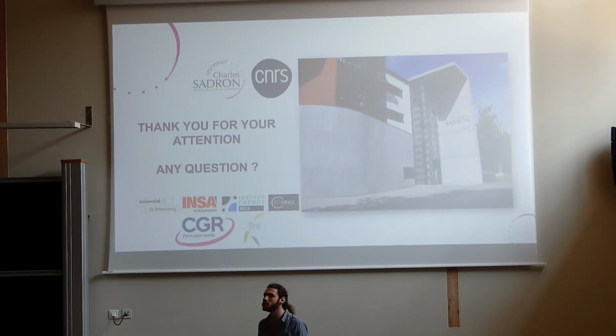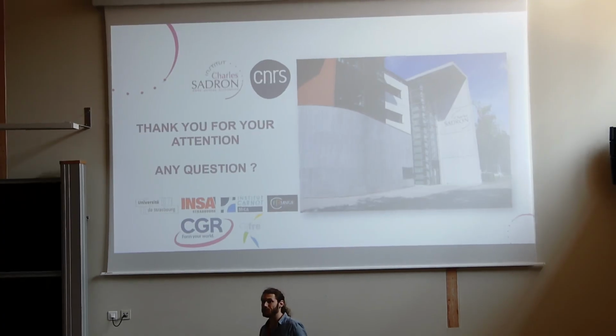Thank you for the presentation. Actually, I have two questions. The first one is, why did you use PEO as a polymer matrix? Historically, there are several publications that show good compatibility between PEO and PEDOT, and the starting point of the work of my former colleague, who made the first strategy I showed before with the polymerization, was to make a PEO-PEDOT composite in solution, and PEO is water soluble. So it started from here.